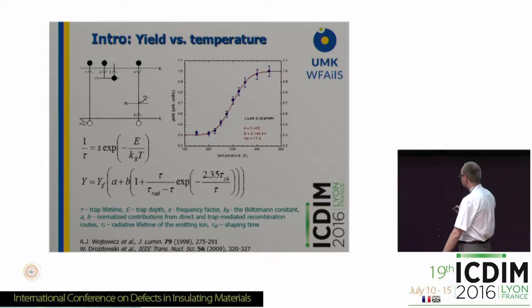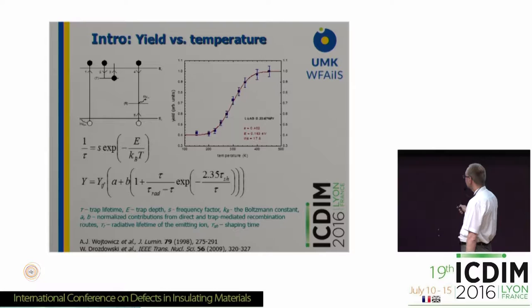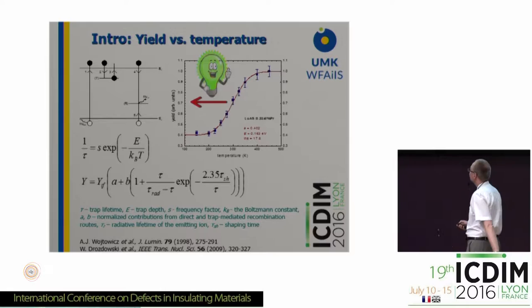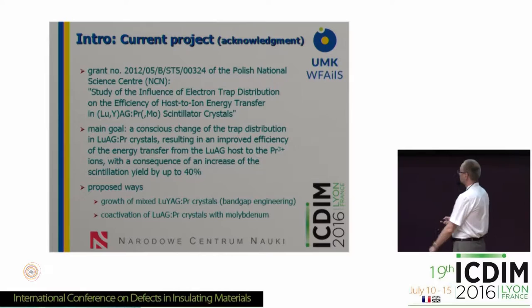We looked closely at the curve which shows the dependence of the scintillation yield as a function of temperature. What we can notice is that the maximum yield for LuAG with Praseodymium is achieved at about 450 Kelvin. We know that this curve is closely related to the existence of electron traps in this material, so the idea was to shift this curve to lower temperatures in order to achieve the maximum light yield already at room temperature.